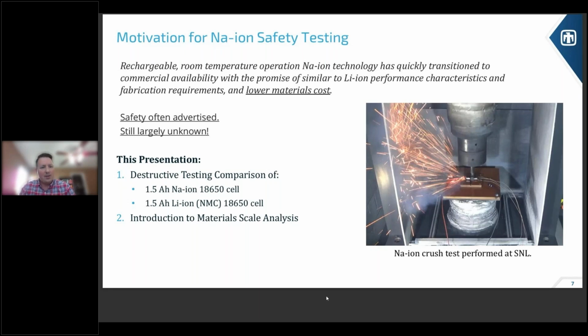Okay, so sodium ion. Sodium ion is a new technology. It's been advertised pretty frequently as safe, but we still largely don't know the safety repercussions of these types of cells. So we were able to obtain some commercial cells through an online vendor, of course, an overseas vendor. So we did destructive testing on the sodium ion 18650 cells. They're 1.5 amp hour, commercially purchased, and we compared those to a 1.5 amp hour conventional lithium ion 18650. And 18650 is the cylindrical type, so the ones that you see in Teslas, or at least a little bit smaller version of those. And also both commercially purchased.